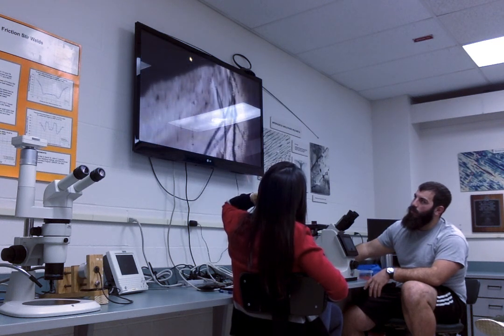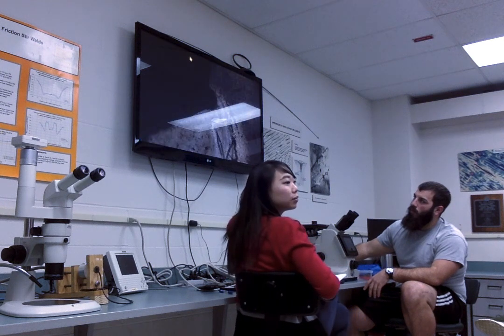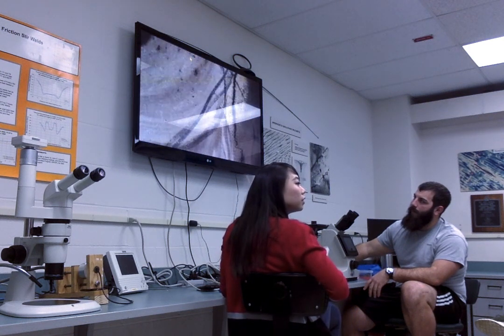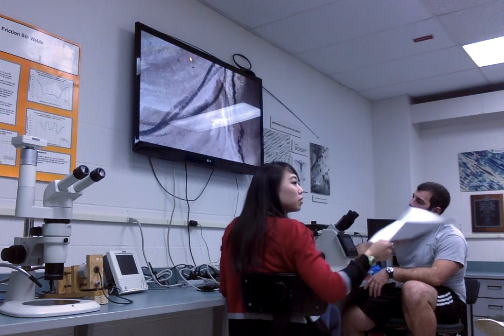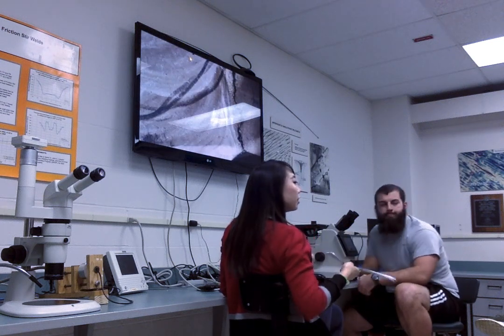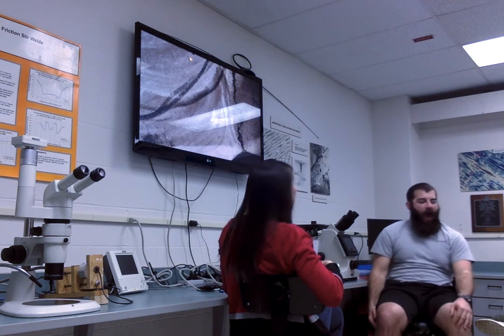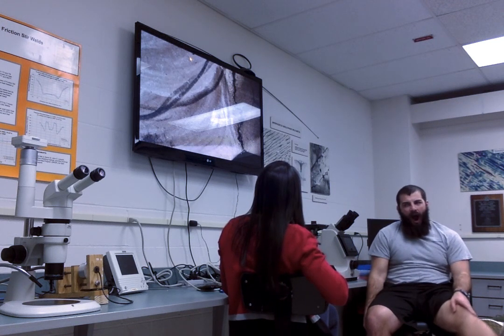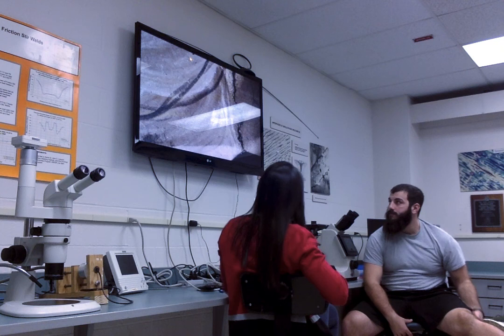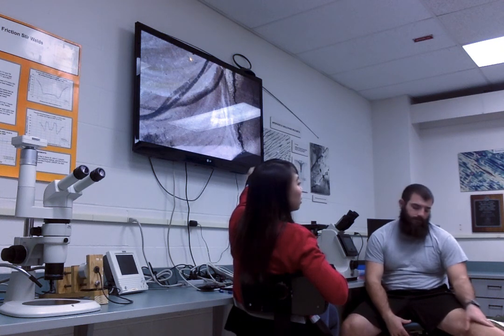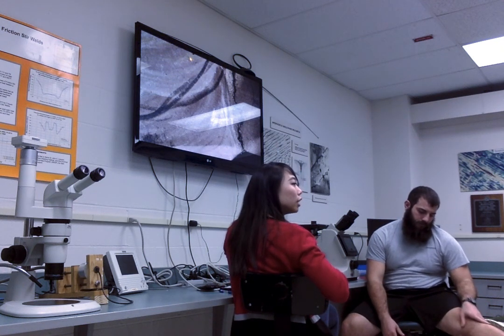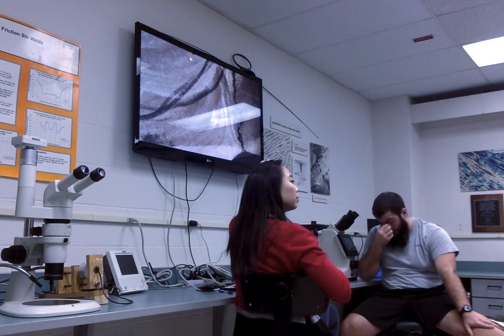Along the HAZ, right. Which part of the heat affected zone? The coarse grain heat affected zone, and why is that? The martensite. Right. So there's a susceptible microstructure there due to the martensite, and it starts at the stress concentrator, so that's where your restraint is the highest in the weld.